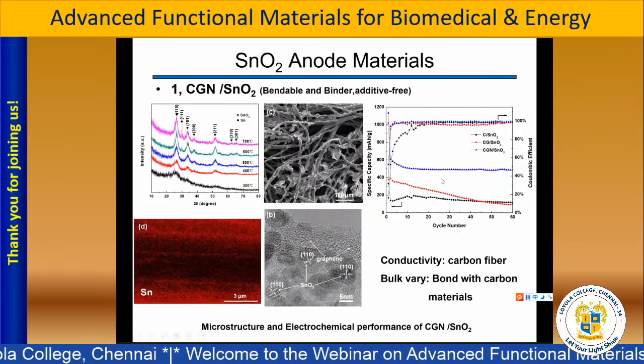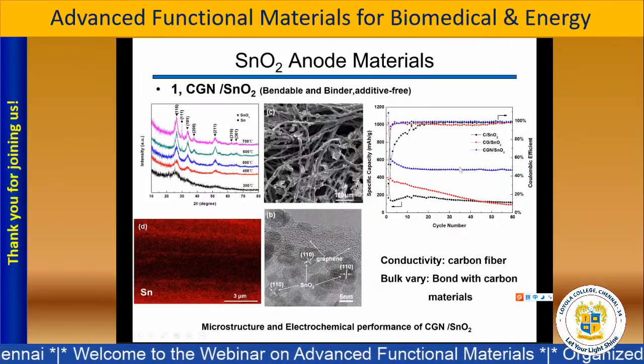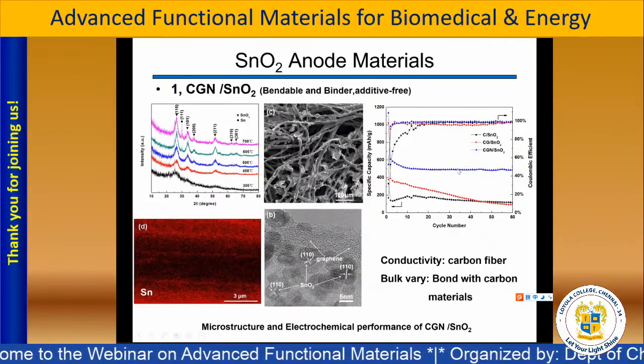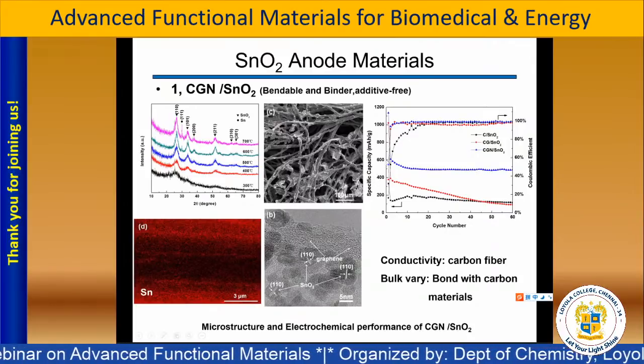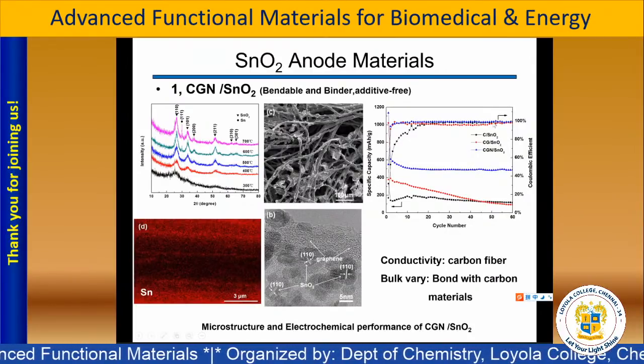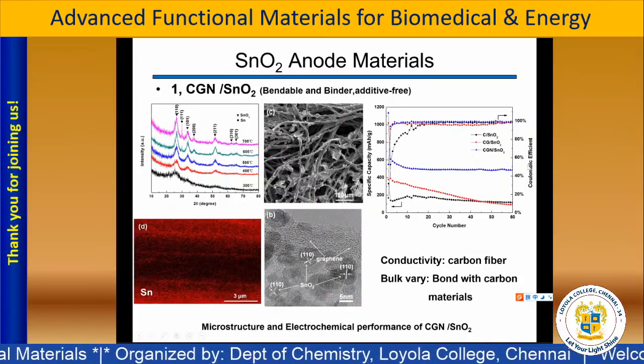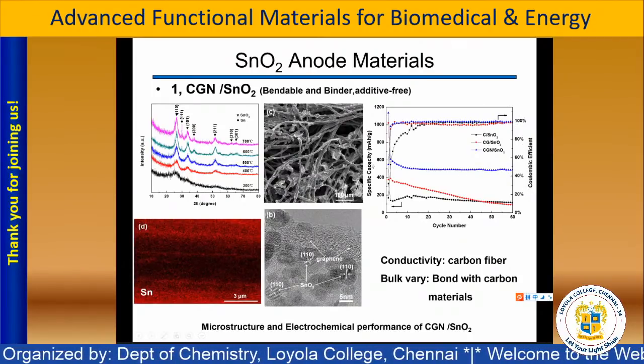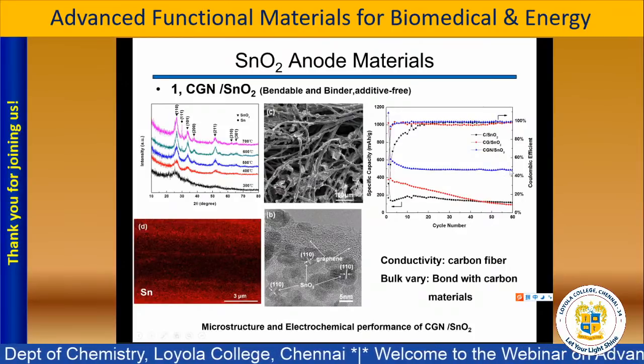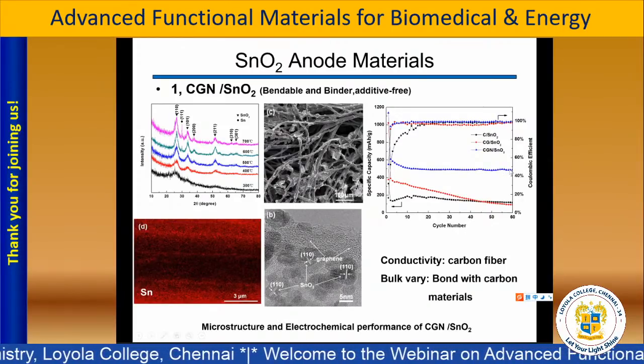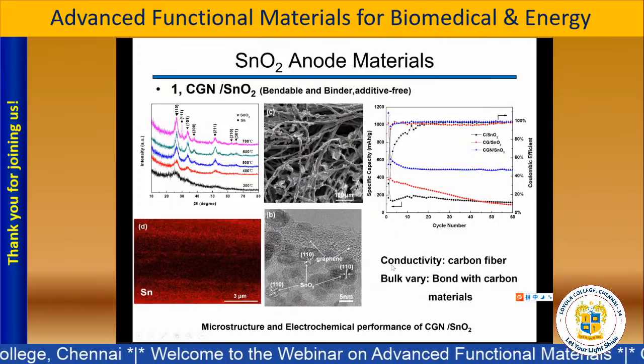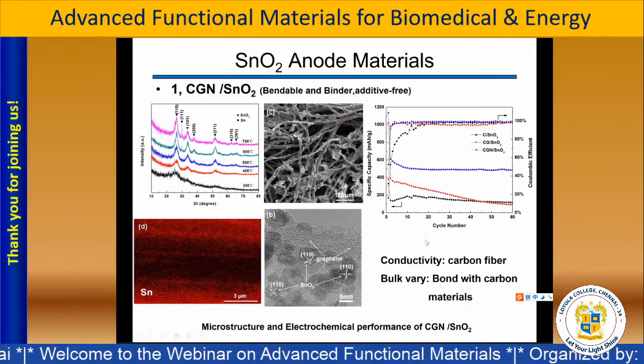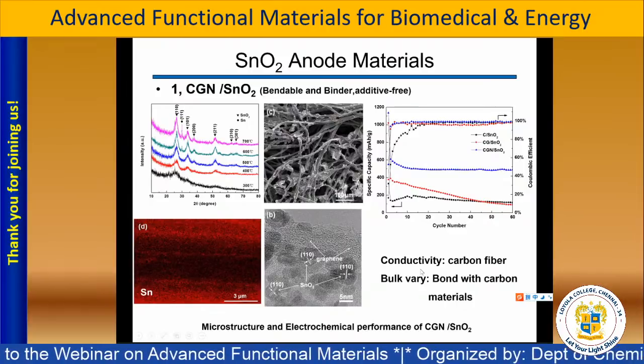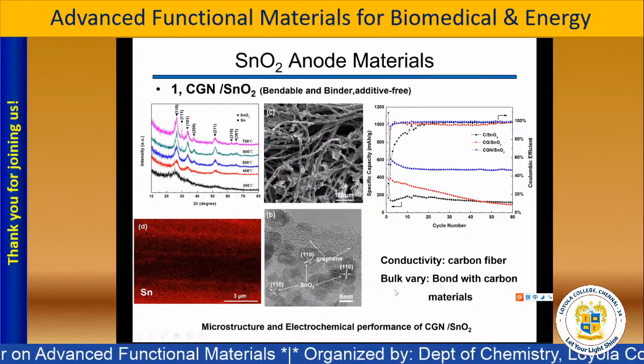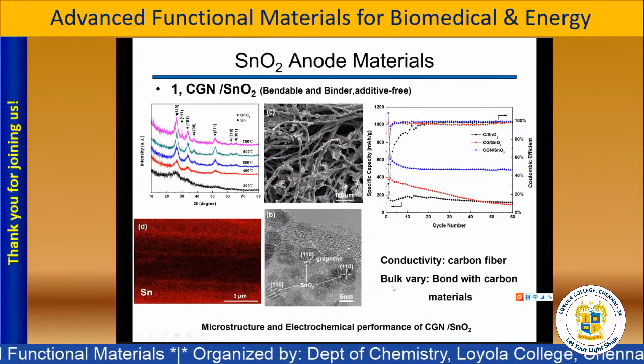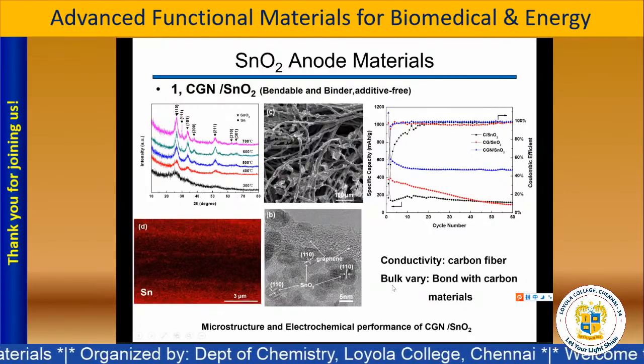So we compare these three materials, and we can see that the CGN tin oxide shows a better specific capacity and a very high Coulombic efficiency. We can see that the capacity can reach a value of about 600, because we improve the conductivity and we use the carbon fiber structure to control the bulk expansion.